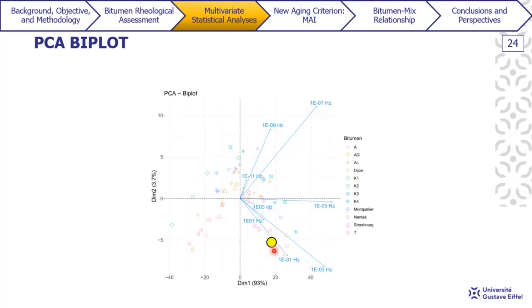Here I put this generic yellow marker here. So with aging, we observe that, first of all, this marker goes from the right bottom to the upper left part. This happened because we have a greater reduction of phase angle values at high frequencies. And then this inflection could be explained by now having a greater variation at low reduced frequencies.